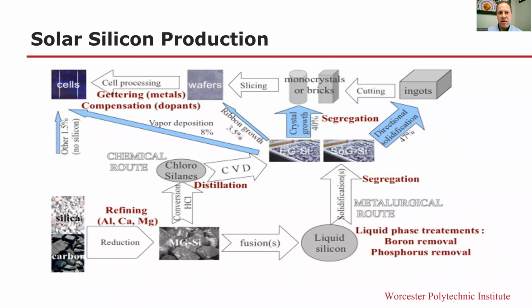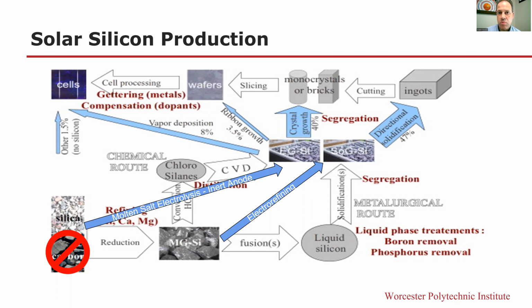This extreme energy inefficiency has motivated the use of other metallurgical routes to bypass this chemical vapor deposition and chlorosilane step. So, for example, you see here the use of liquid metals. In addition, one can also use electrorefining to directly refine metallurgical grade silicon into solar grade silicon potentially, though that requires first blending it with another metal such as copper. But what if we could eliminate the carbon altogether and use an electrolysis route to go directly from silicon dioxide straight to silicon? So that's what we are working on in this project here.